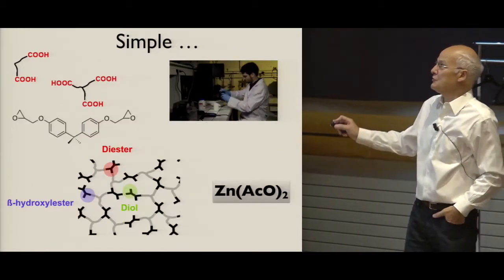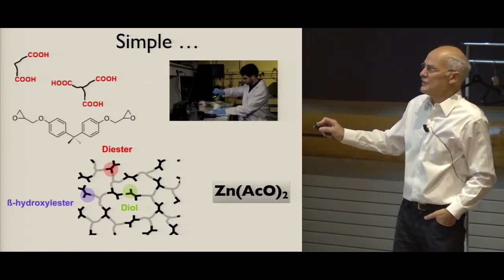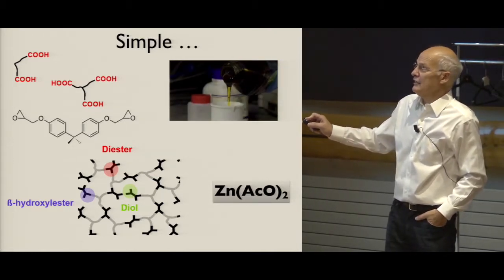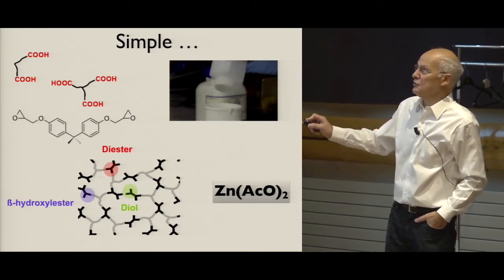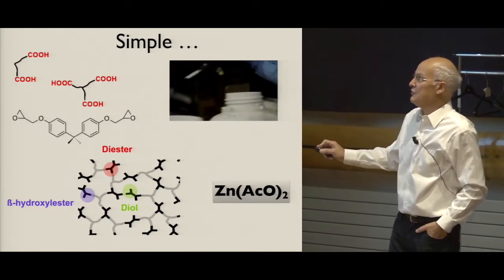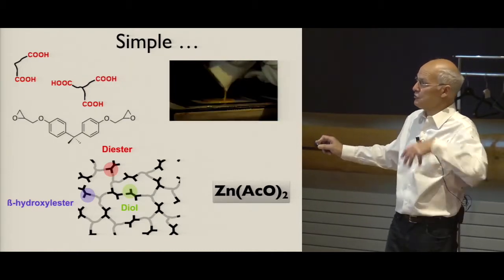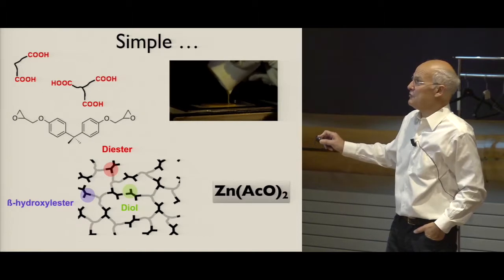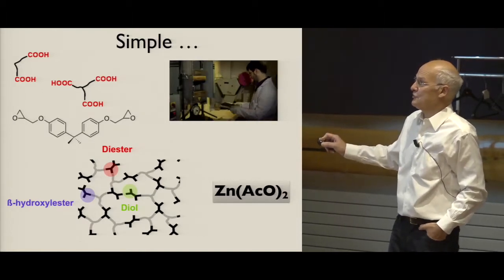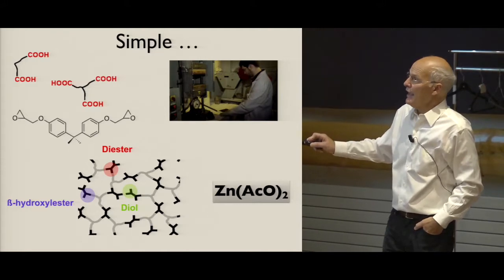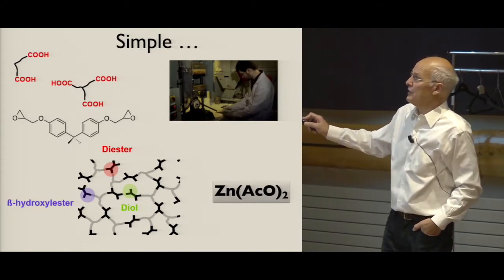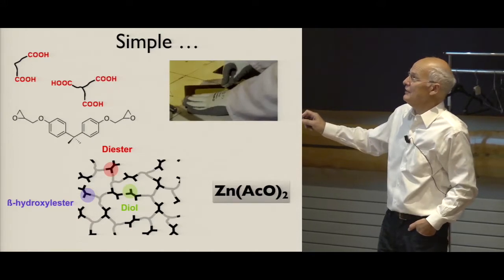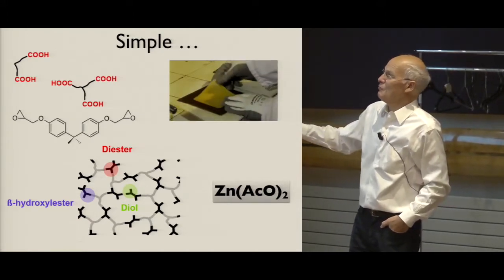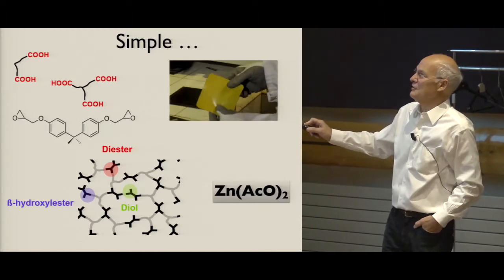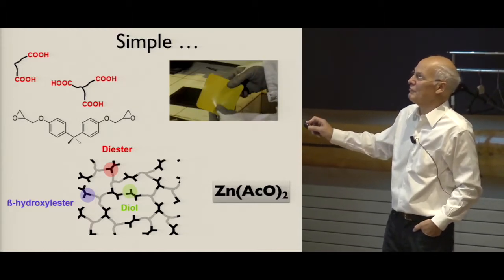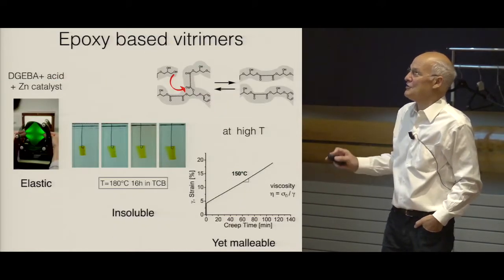And the chemistry we use, so this is Mathieu Capelot, we knew in the lab the epoxy chemistry, and instead of doing it with amine, we did it with acid or anhydrides. We added just the transesterification catalyst, which makes this reaction rapid at the conditions we wanted, which is maybe 200 degrees or something like that. And then we obtain a vitrimer. As you can see, the chemistry is not extremely complicated because it's epoxy, and you can make it at a 200 grams scale very easily.